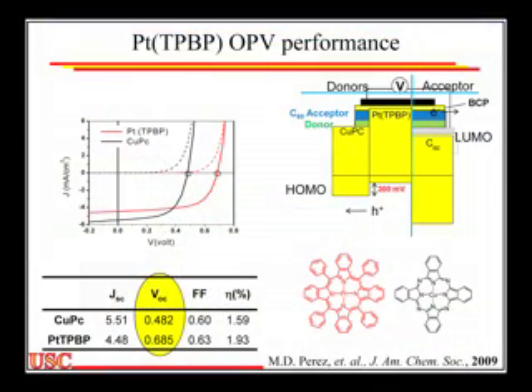So the red trace is the platinum porphyrin, the black trace is copper phthalocyanin. And this looks good. We get a nice efficiency, we get a big efficiency bump going to the platinum porphyrin, and that was a benefit. But the thing that was a serious surprise was this open circuit voltage. This was not what Dolores expected. She expected exactly the opposite. She expected the platinum porphyrin to have a lower potential than the copper compound.